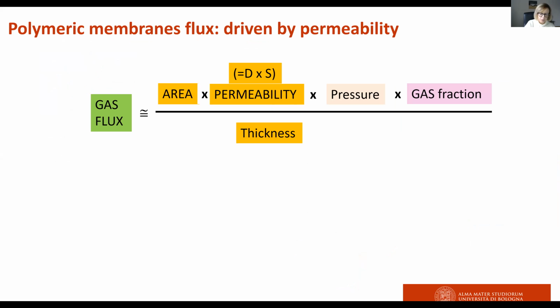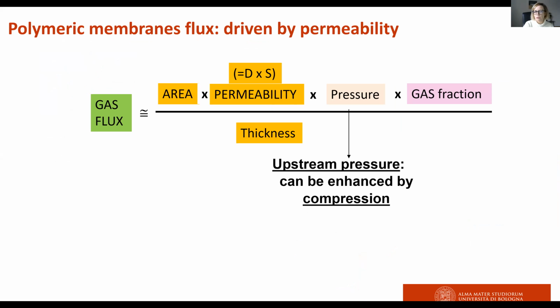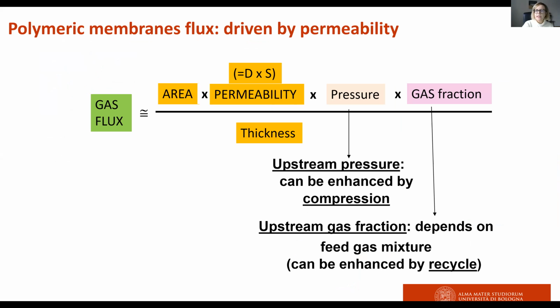So speaking about operative parameters, we have parameters which can increase the flux of CO2, which are related to process conditions, such as the pressure, which can, of course, be enhanced by compressing the upstream feed or by reducing the pressure of the downstream one. The gas fraction in the feed can only be increased by introducing recycling loops in the process configuration. On the membrane side, we have other parameters, which are the area, the permeability of the membrane, and the thickness.